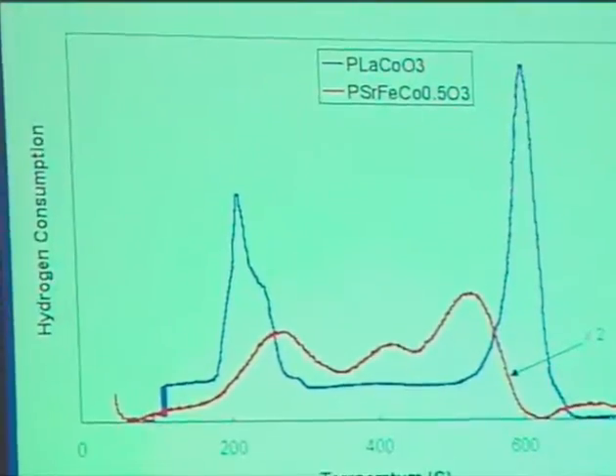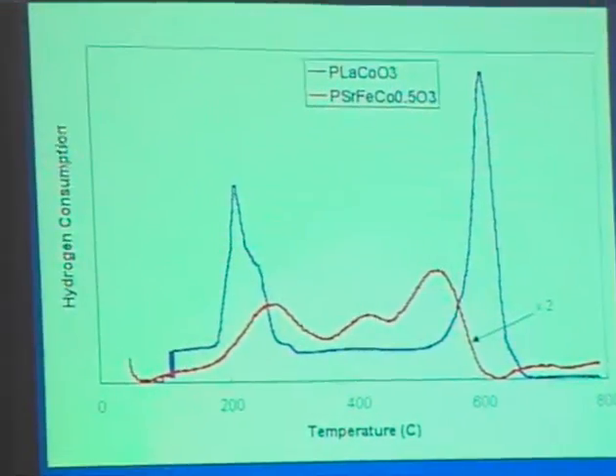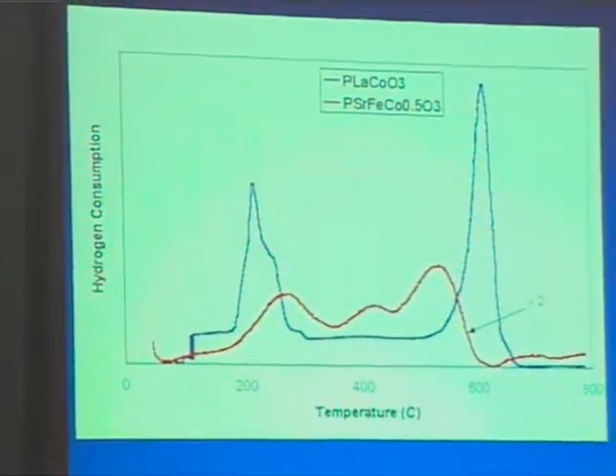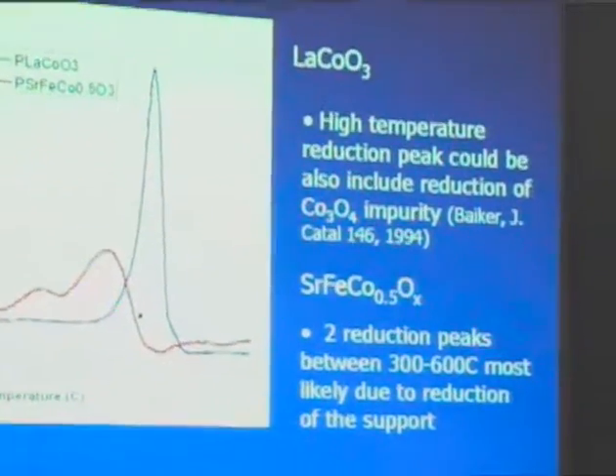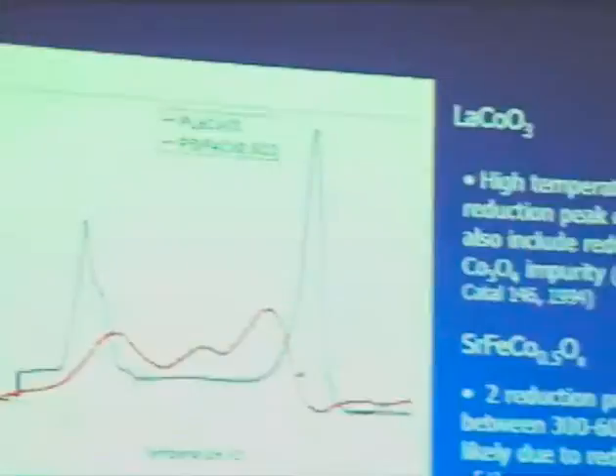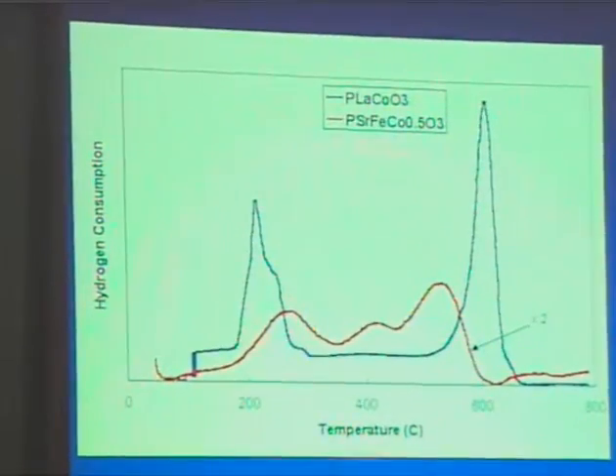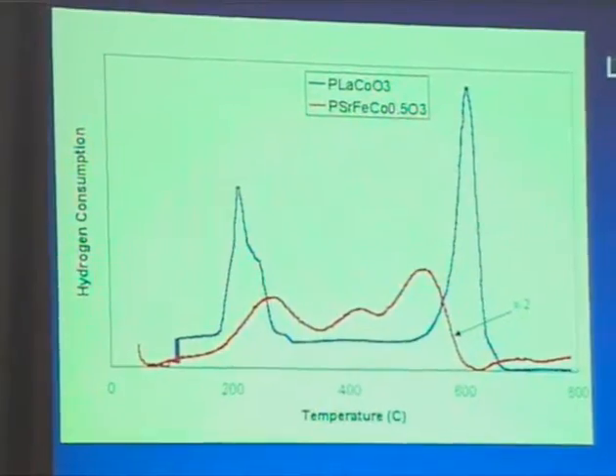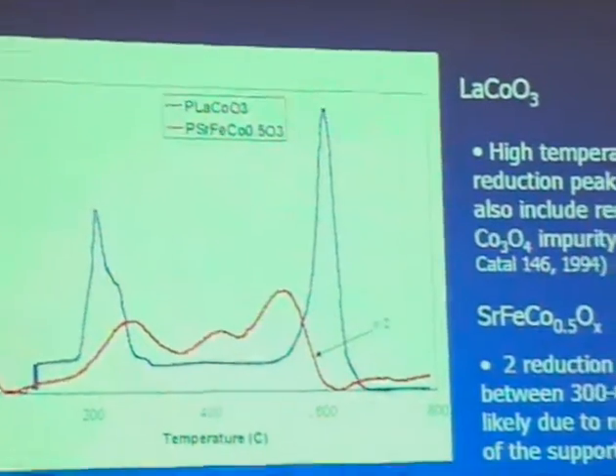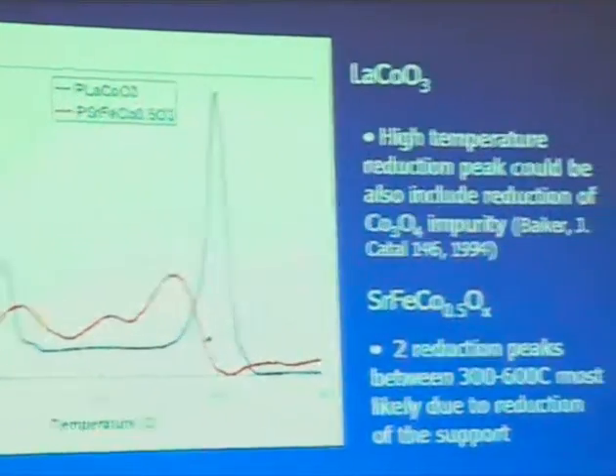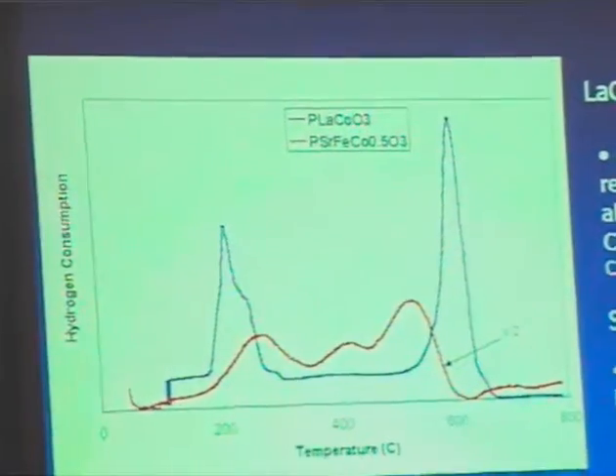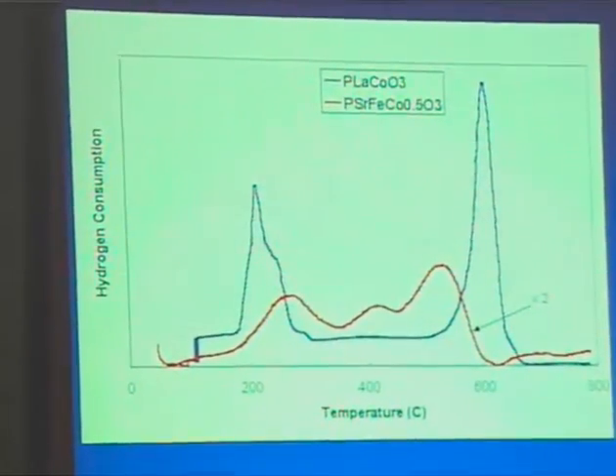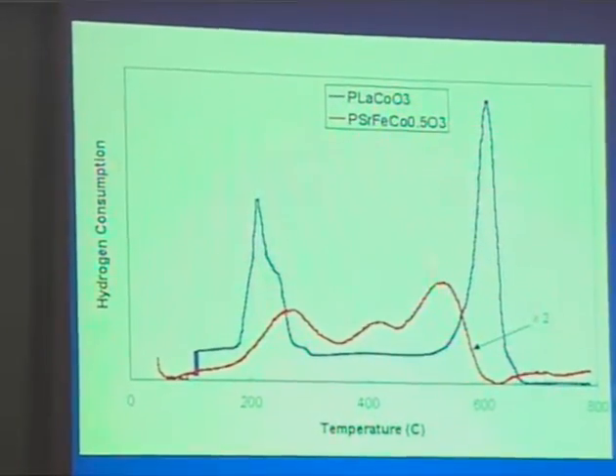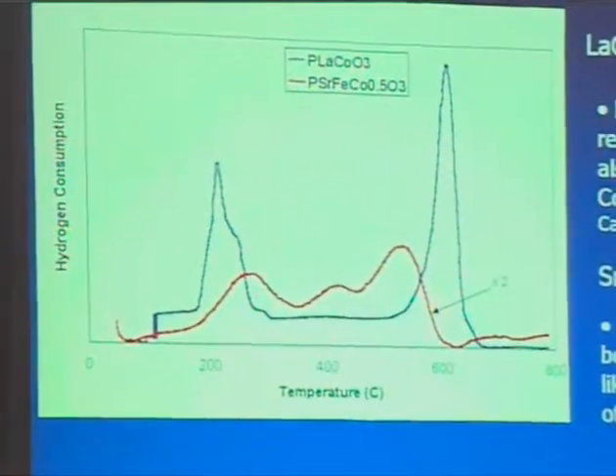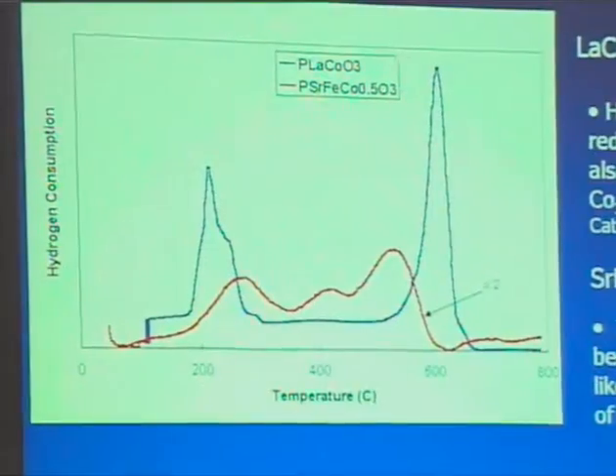Temperature programmed reduction experiments on the perovskite and the strontium iron cobalt show that you have reduction of either the formation of La2O3 of this material, or it could be due to cobalt oxide species that are being produced. And it's been shown that if you use the citric acid method with nitrate materials in the preparation, that you can have this material on the surface, which would then be reduced, forming a peak around 500 to 600 degrees. So this peak could be due to the presence of both of those reductions occurring.